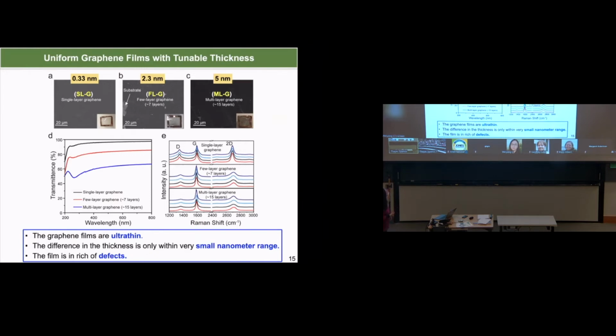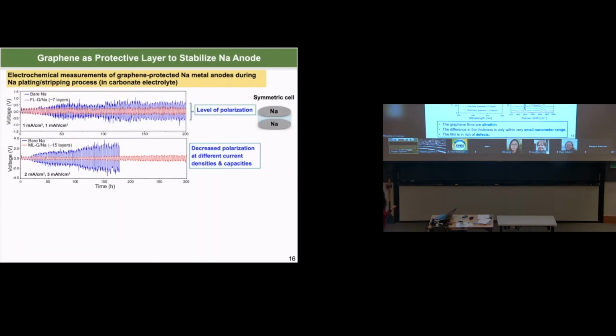I also want to mention that the film is actually very rich in defects. Why this is important is because you want the sodium ion to be easy to diffuse through this graphene film. Because if the sodium ion cannot move through the film, you are not going to have sufficient ion transport.